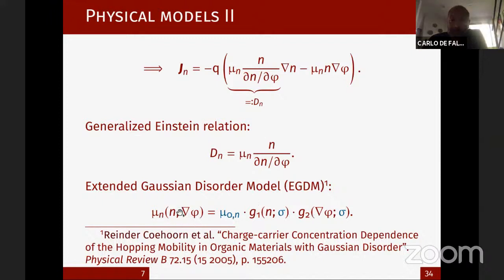But even if this relation is smooth, as we have seen in the 2D pictures before, the density of charges and the electric field display very steep changes within the device. So even if this coefficient is not discontinuous, it is effectively discontinuous because it changes a lot in a very small range of space distance. So this is to justify that our numerical method will have to deal with currents that do not respect the Einstein relation. So this is the first requirement, and still be thermodynamically consistent in the sense that I will explain later.